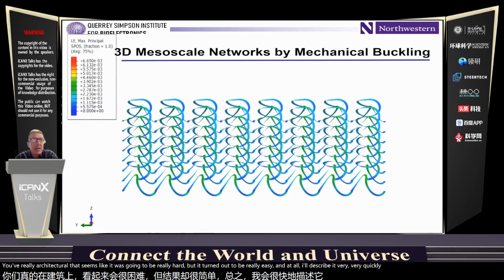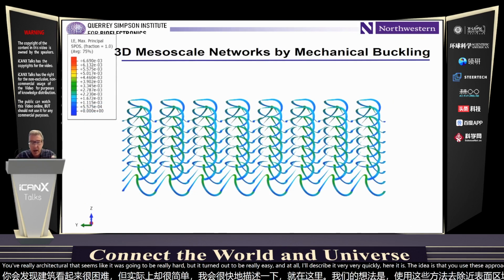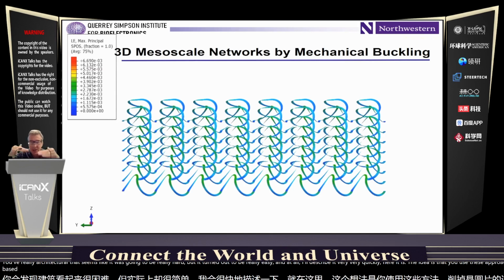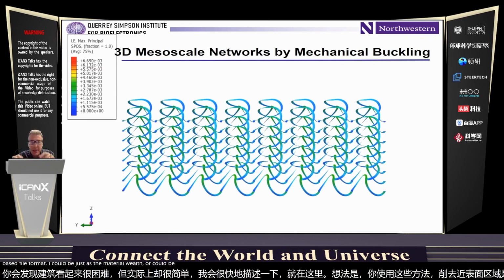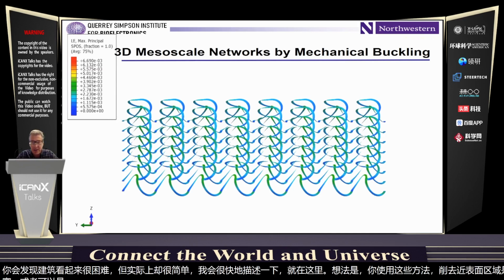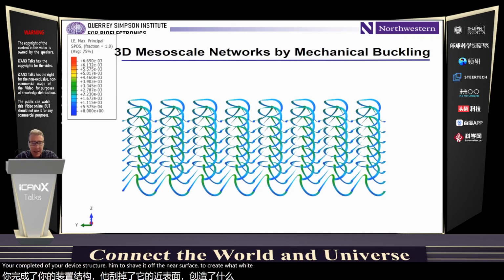And the idea is that you use these approaches in shaving off the near surface region of a wafer-based platform. And that could be just at the material level, or it could be completed device structure. You shave it off the near surface to create what in this particular example is kind of an open filamentary mesh type structure. And then you move that mesh to a pre-stretched elastomer substrate. And you've configured the mesh such that when it comes into contact with that pre-strained elastomer, it bonds selectively at certain locations. And then you release the pre-strain in the elastomer.